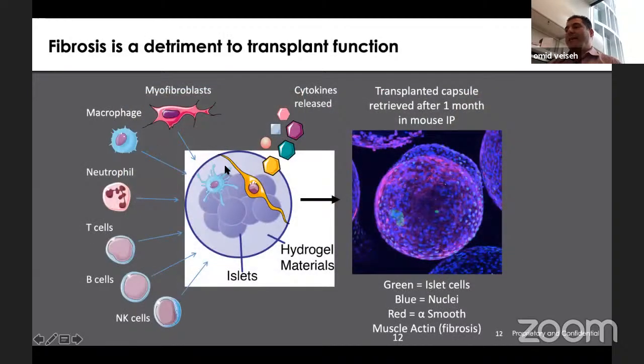And what we know is that alginate, its composition is such that the host immune cells, in particular macrophages, recognize alginate polymers as a foreign substance and basically attach to the surface of these capsules and become activated and release cytokines, which further recruits myofibroblasts and other immune cells. And ultimately, after a few weeks, you end up with this matrix of extracellular matrix that has deposited